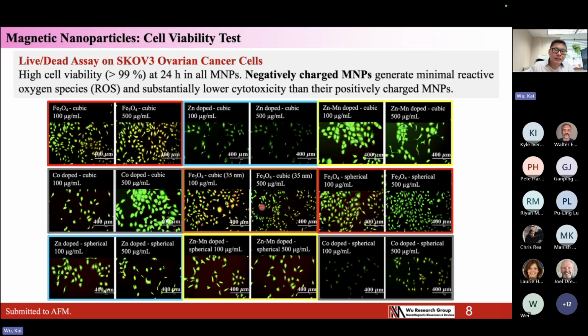Next, we calibrate the cell viability, or the biocompatibility, of these particles in the SKOV3 ovarian cancer cells. We incubate two different concentrations, 100 micrograms per milliliter and 500 micrograms per milliliter, of particles with the ovarian cancer cells. As we see from all the figures here, the cells are highlighted by the green color. You can also see some red color of cells, a very minor amount, as you can see from the laser point here. The red color shows that the cell is dead. The green color shows that the cell is still alive.